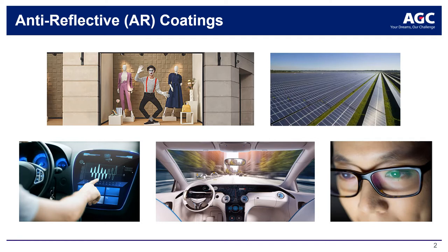Anti-reflective coatings can be found on architectural glass, for example. By reducing the total glass reflection coming from both surfaces from a level of 8% to a level of 1% for a double-sided coated anti-reflective soda-lime glass sheet, the glass appears highly transparent and does not reflect its surroundings. Objects behind the glass are more clearly visible and can be shown off to full effect.